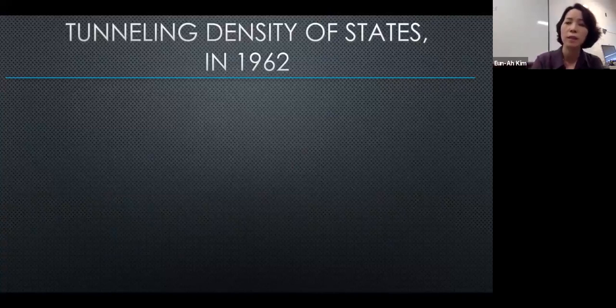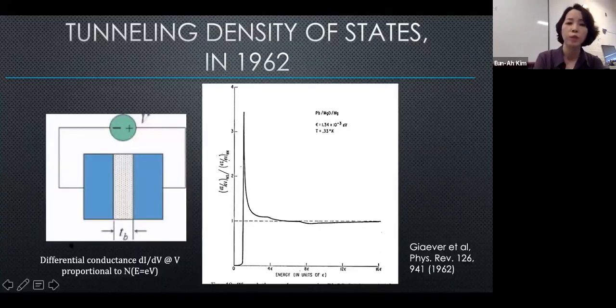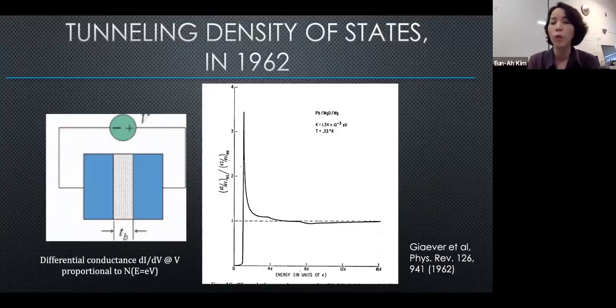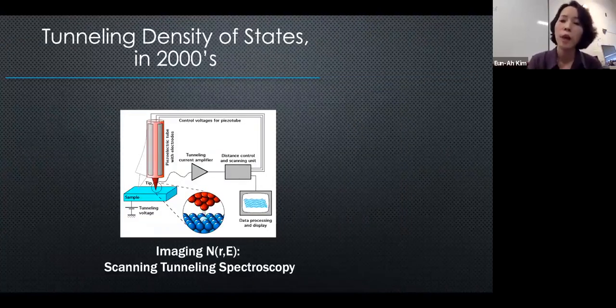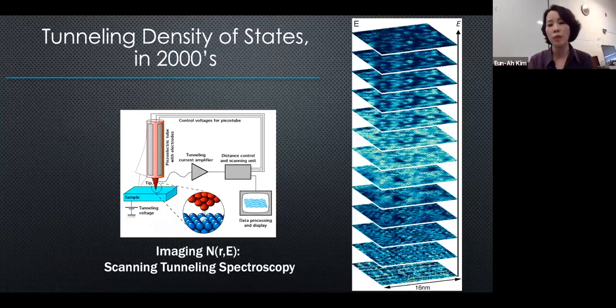Tunneling density of states in the 1960s was measured through a macroscopic tunnel junction, as shown here. And what one would measure was a curve. We understand every aspect of this curve, not just the suppression, not only the peak, but we also understand these little wiggles. We have models that are very satisfactory for this entire curve. But we wanted to understand more about the materials. We discovered more complex materials. And coming to 2000, the amount of information we have is not a single curve for a given sample, but a whole big collection of curves, or a layer of images. And we don't have a satisfactory model to describe these data sets, nor would we have hope in coming up with such a model.